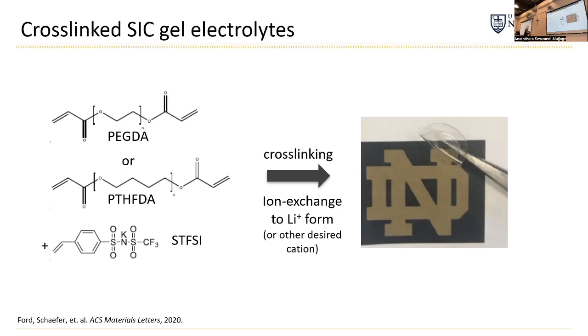And we had a hypothesis that the dielectric constant of the polymer media was really important. So he was comparing this commercially available material with this one here that we made in the lab, where this is poly-THF diacrylate, we just have more carbon atoms. So the density of the oxygen is less, so the oxygen atoms are further apart. And we thought that that would be important for how the polysulfides would interact with the membrane. And at the time, we were doing work on those other types of ionomers that I mentioned earlier. And he just decided on his own that he was going to ion exchange these, and he was also working on magnesium sulfur systems. But he decided to ion exchange his materials to the lithium form, and he wanted to study them as single ion conductors, as a side project.